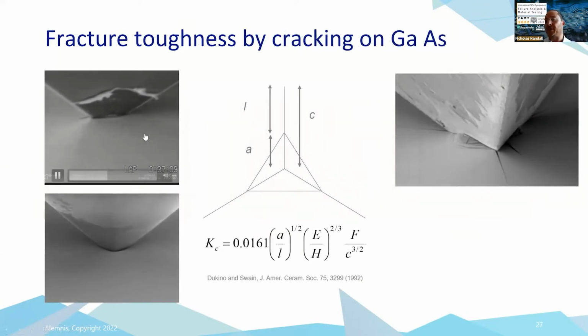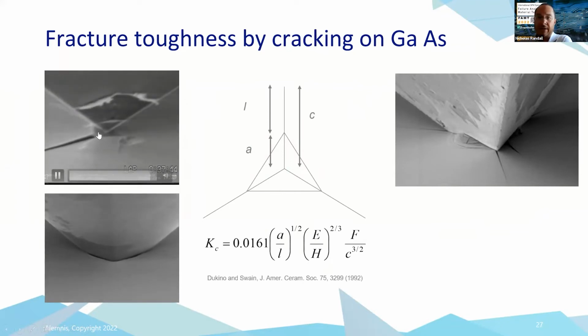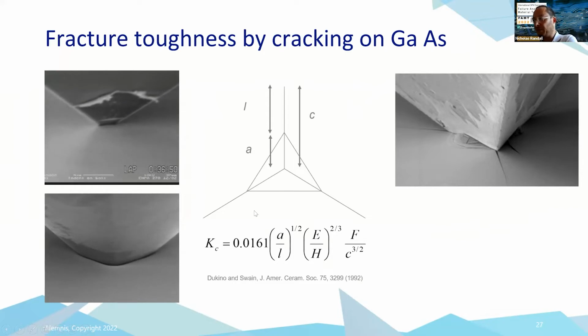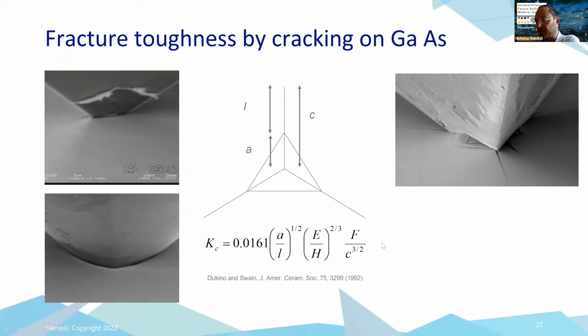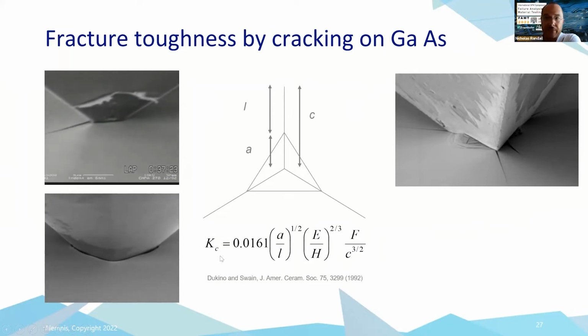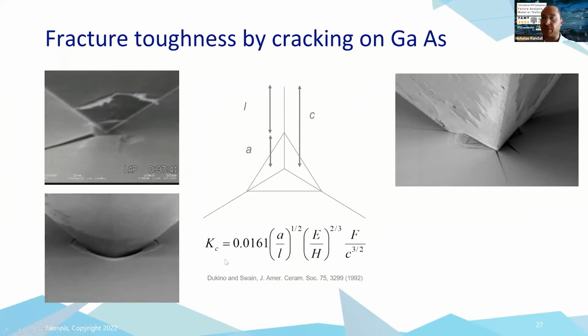Another way of doing it is to make the indents and measure the crack lengths. So you can see here we're cracking in gallium arsenide, and then we can put the crack lengths into this simple equation. So F is the load, C is the crack length, E over H is the modulus to hardness ratio, and these are the crack sizes. And this gives us Kc, which is the fracture toughness of the material.